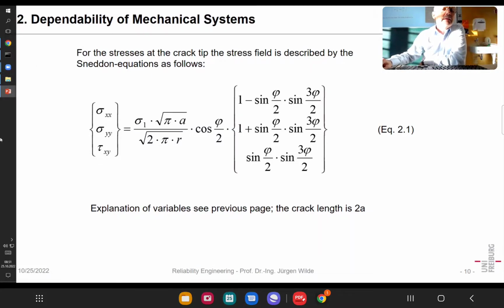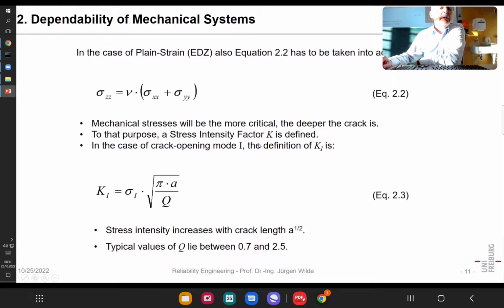And what is important here is, I said, the stress is proportional to the inverse of the square root of the distance from the crack tip. But on top here, you can say the stress scales with the nominal stress, that's just force divided by the complete area, multiplied with a factor that is the square root of pi times the crack length. In that way, that defines the stress intensity, and that defines the position around the crack, and in that way, that stress field can be computed.